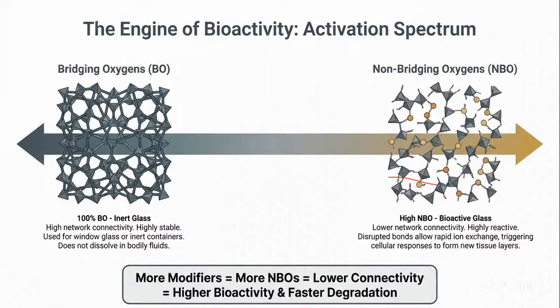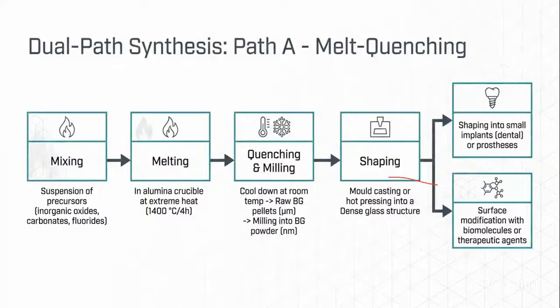If you increase the modifier content, eventually you are increasing more NBOs. If you are increasing more NBOs, then the connectivity of the network is lowered. If the connectivity of the network of the glass is lowered, that means the bioactivity is increased. And if the bioactivity is increased, then the possibility of degradation is also much quicker. So these are the things that we need to remember.